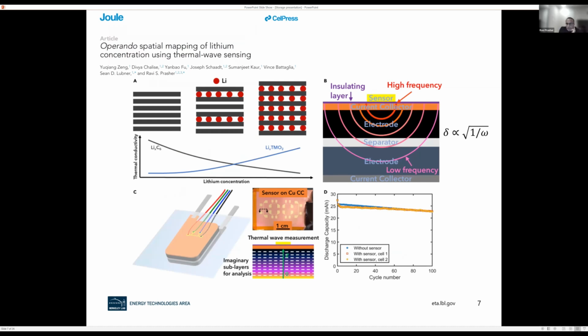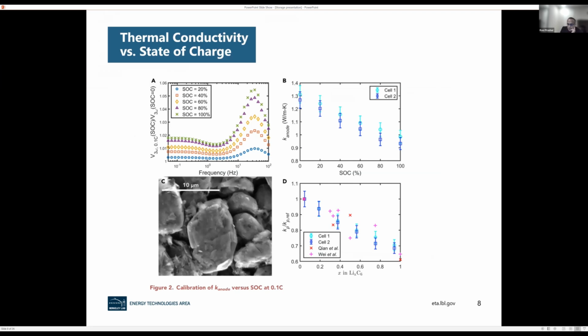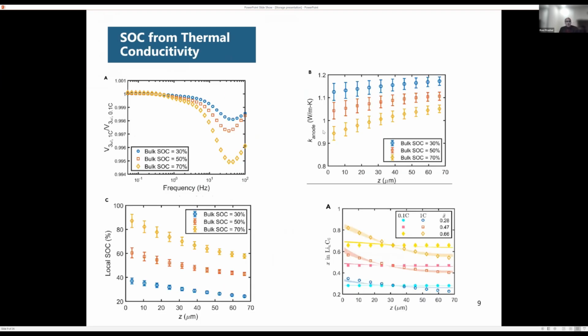That's a great question, by the way. As I showed you, we are able to predict it with a fairly good error bar, here. So you can see that we actually resolved the spatial distribution. I think your question is about resolution: we cannot do better than 10 microns spatially. That's why you can see the data is almost every 10 microns. With this technique, 10 microns is probably the best. We have another technique in the works which can go to nanometer scale.